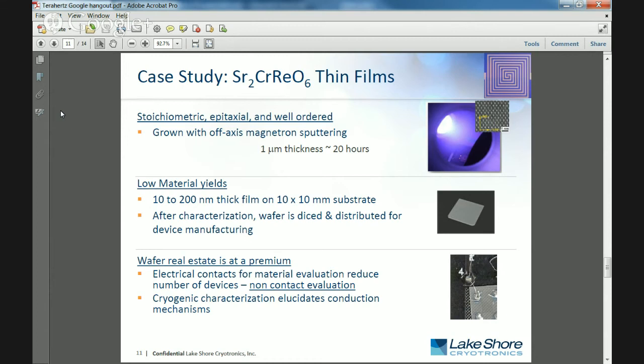And so what we found is that wafer real estate is at a premium. Electrical contacts are basically going to reduce the amount of material that's available for other characterization. A non-contact evaluation technique like terahertz, I think, is really useful and powerful for materials like this. And then we want to toss in the cryogenic characterization because it allows us to vary the conductivity in the material and see how this conductivity changes with temperature. And so we pop over to the next slide.